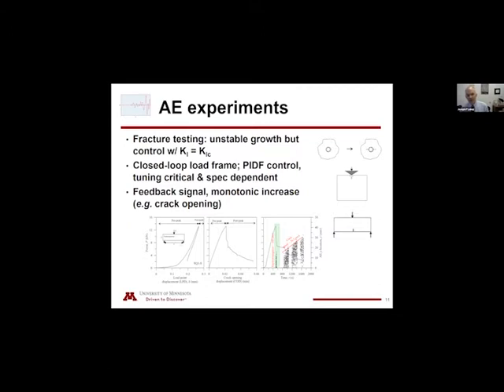For example, I'm showing here results from a beam test that has a smooth boundary, that is, no notch. This is the force load point displacement response. And you see the post-peak behavior, which we'll be assuming in the analysis that I'll show at the end of the talk. Assuming linear fracture mechanics is valid, we have a balance in the energy release such that any point within the post-peak response is associated with the stress intensity factor K1 being equal to a material parameter, the fracture toughness. And you see the strong snapback response occurring with the load point displacement, whereas the monotonically increasing parameter is the crack opening displacement.